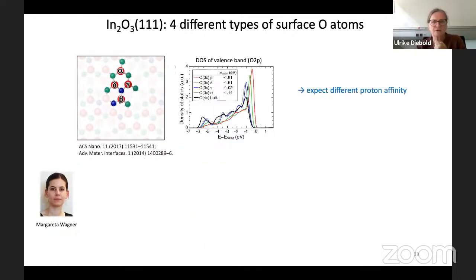And because of that, the reactivity of these oxygen atoms is a little bit different. So we named them alpha, beta, gamma, delta. These are theoretical calculations of the valence band density of states. And if you look at the HOMO, the higher the HOMO, the more reactive. So you would expect the beta oxygen here to have a different proton affinity than, let's say, the alpha, gamma or delta oxygen atom. Similar to molecules, depending on how they are bound to the backbone, it will be different how easy it is to give off this proton.